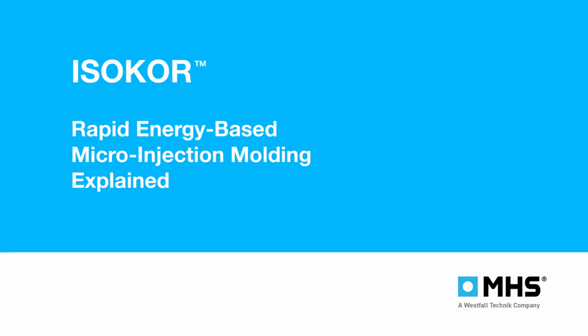The straitjacket is a perfect visual. The pressure protects the chemical integrity of the material. According to the MHS data, this constant pressure environment actually extends the allowable melt residence time by a factor of 5. 5 times as long. That's insane. Right. Material that would normally degrade and turn brittle in 10 minutes can safely sit in the highly pressurized MDU for nearly an hour without losing any of its mechanical properties.